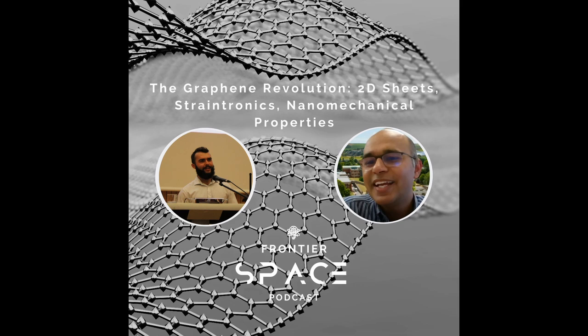Yes, we were wondering about the grain boundaries and the different kinds of wrinkles. Talking about the nature of the wrinkles, let's start from something. When the graphene is flat, there is no defect, no structural disorder. When there is a hump of less than or around 1 nanometer, it is considered in the category of ripples. When you do nanoscale imaging, it looks like a wavy structure, like the waves we can see in the oceans, small tiny humps. When this hump goes from 1 nanometer to 8 nanometers, it changes the property because the gap is increasing. So it becomes a standing collapse wrinkle.